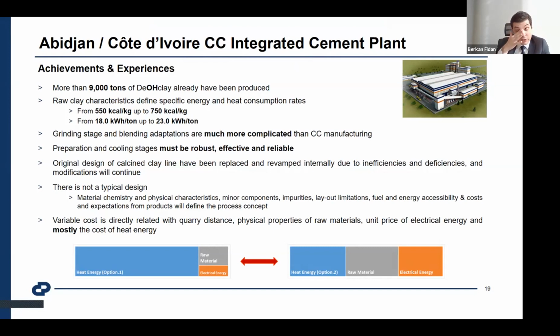In our first remarks, there are many issues people are sharing and technology suppliers are giving, but in the exact field results we saw that the specific heat consumption is between 550 and 750 kcal per kg. Its range is high, but it's related to the raw clay moisture content. There are many effects on it, and we are at the optimizing stage. We believe we could keep it between around 550 and 650. The specific electricity consumption is between 18 and 23 kilowatt hours per ton. That deviation is also related to the capacity options.